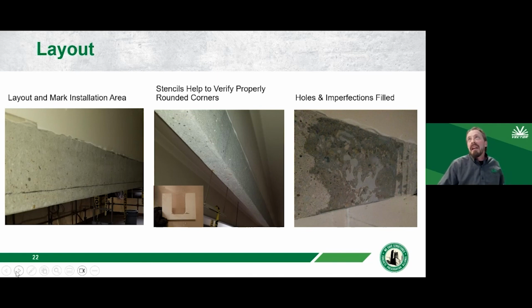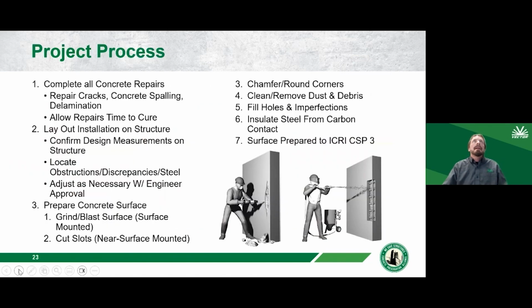On the right-hand side, you see that there is some epoxy installed on the bare concrete. That's to fill in any sort of bug holes or imperfections. So we don't want any sizable bug holes or imperfections on the concrete, because that is a break between the FRP material and the concrete itself. So we don't want any barriers or any voids there.